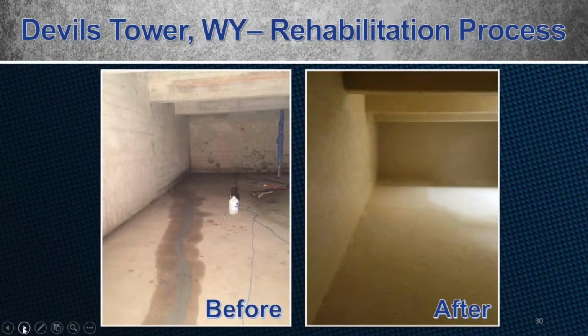Approximately 2 hours after the epoxy mortar was used, if you notice in the picture before, the guy was applying the mortar to fill all the bug holes, the 100% solids penetrating epoxy primer, the Raven 171 fast set, was applied by roller at 6 to 10 mils dry film thickness over the entire surface. The epoxy primer was used to lessen the outgassing of the polyurethane finish coat that was going to be applied soon. The epoxy primer was allowed to cure overnight, just because of the timing of the project itself, before the polyurethane lining was applied.